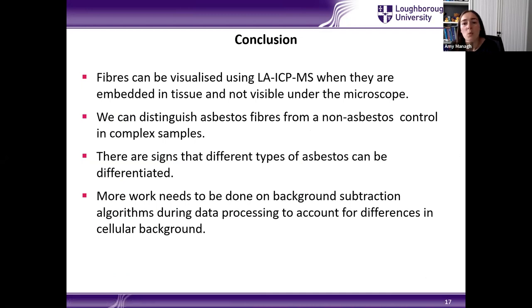So to conclude, we can visualise fibres within laser ablation ICP-MS data, even when they're embedded in the tissue and aren't visible to us under a microscope. We were able to clearly distinguish the asbestos fibres from a non-asbestos control sample, even in these complex samples. And there were actually signs that different types of asbestos can be differentiated from each other, although we would want to collect a larger data set in order to fully confirm this. I think there's more work that we need to do in this area as well.